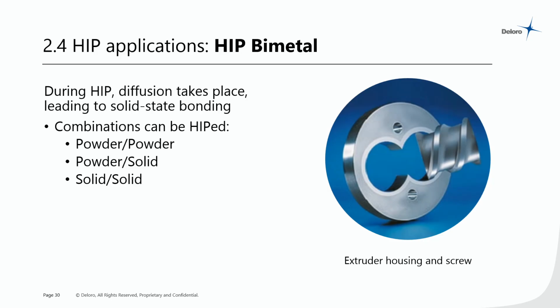Right, and then finally, a fascinating application for HIP, which we've been working with a lot lately at DELORO Wear Solutions, is using HIP to bond a hard wear-resistant alloy or a corrosion-resistant alloy to perhaps a steel body or a steel component. And you can bond powder to powder, you can bond powder to solid, you can bond solid to solid, which is really just diffusion bonding, actually.